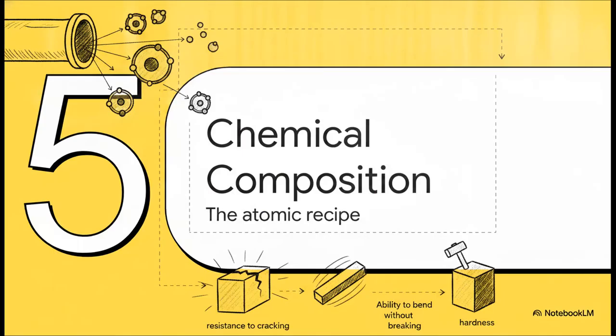And to pull that off, it requires what's called fully killed steel and incredibly clean steel-making practices to guarantee maximum toughness. And that brings us to our final phase, phase 5, chemical composition and designations. So the crucial takeaway here is that everything we've talked about, from hardness to crack resistance to the ability to bend without snapping, is ultimately dictated by the steel's atomic recipe. And because oil and gas is a truly global industry, API 5L acts as this universal language. For example, an API grade L415 maps directly over to the European steel number 1.8725.